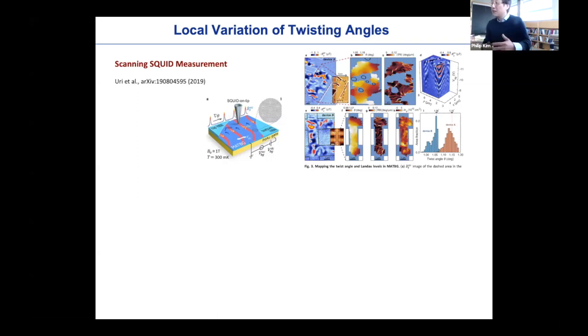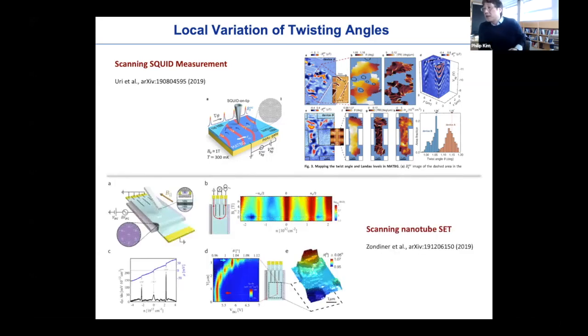But if not, then you just don't read it. So certainly we can imagine that sample inhomogeneity plays quite an important role when you use transport as a tool. And a very similar experiment also shows up in this case, scanning SET made of the nanotube, done by, again, the Weizmann group to demonstrate this imaging capability, which shows the fine distribution of the angle in the system.